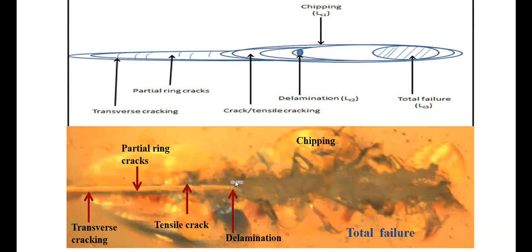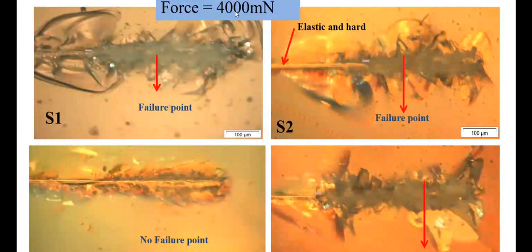So from here to here, the force which we apply on the needle will increase as it goes further. From here, with 4 Newton force, we get the failure point in S1. The failure point in S2 has also resulted. You can see the failure points in S1 and S2. But in S3, no failure is observed with 4 Newton. And the failure point is again observed in S4 at high dense cross-linking density, which turns out to be more brittle. The coating tends to be more brittle. The organic coating becomes more brittle due to higher cross-linking densities.